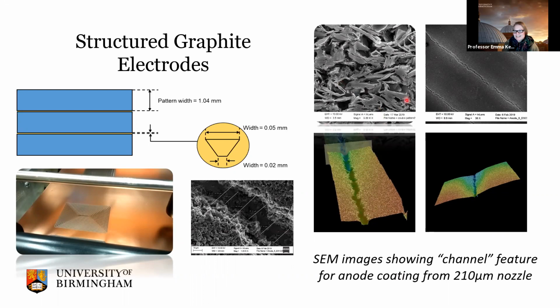Now, I think it's interesting because we can form structured electrodes like this, and we can get improved performance properties in a half cell using a lithium metal counter electrode. But when we come to use it in a full cell, for example, then I think that's a really quite interesting question. Where does the lithium go? What is the current density at different points? And do we end up then having a mismatch between our anode and cathode because of this effect? So I think that's a really good question and something that we haven't quite got around to answering yet. Thank you.